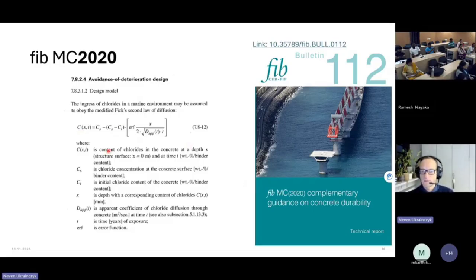This is from the original model code. So basically it's just a diffusion model, a modified second Fick's law. We have here the apparent diffusion coefficient. Why is it apparent? Because it includes all the parameters, since it's a very simplified model. We don't have only diffusion, we also have reaction and convection, or many things happening. But if you simplify it only as diffusion, then this parameter is apparent. The most important part is the reaction, the binding of chlorides, and this is why it is apparent.